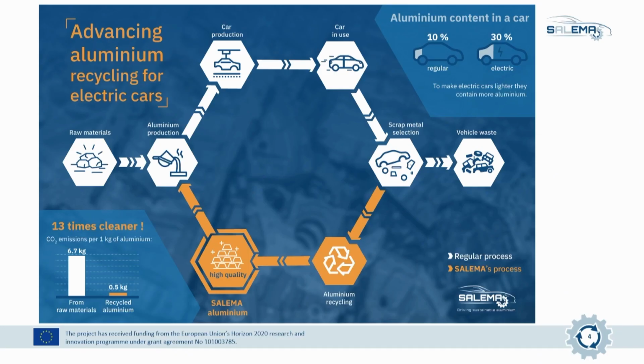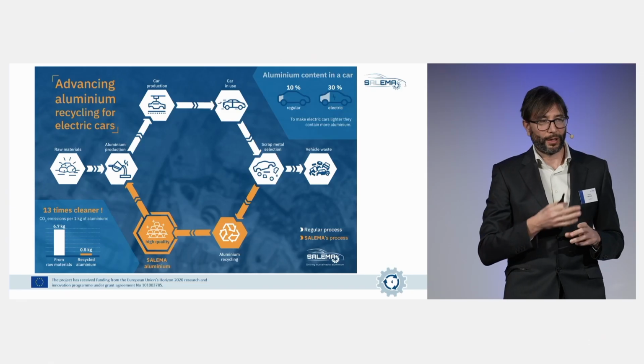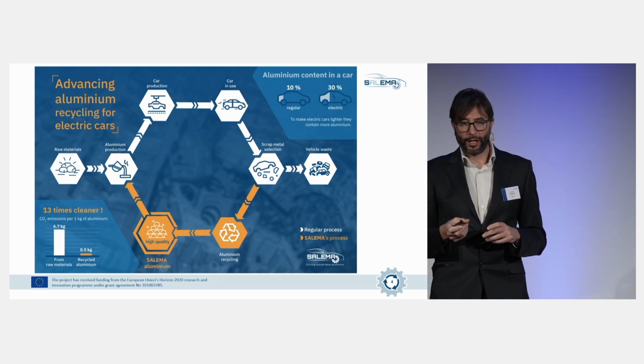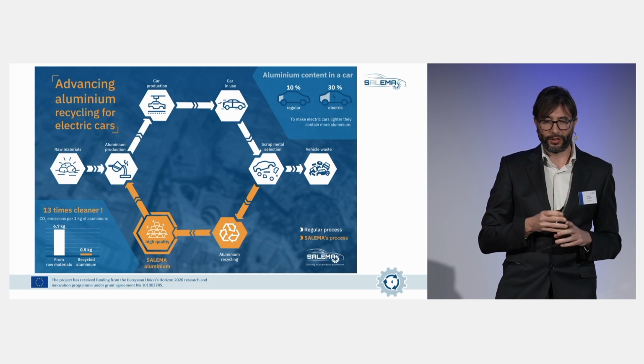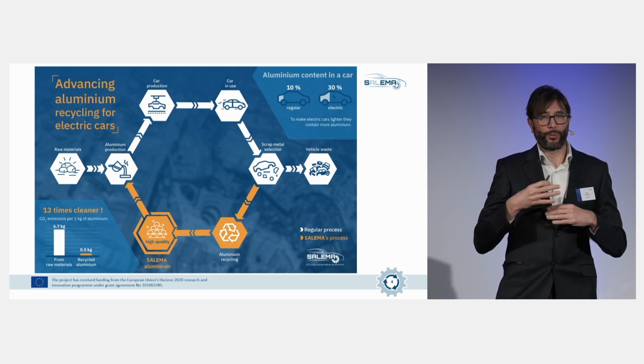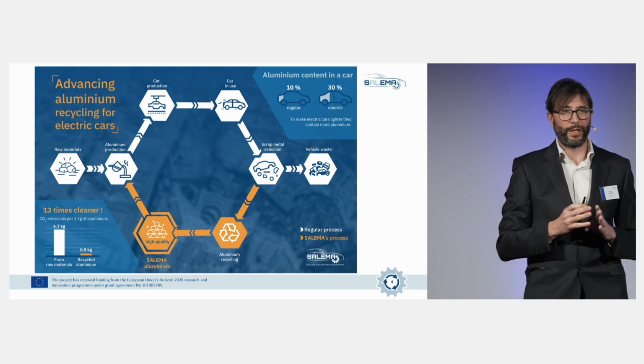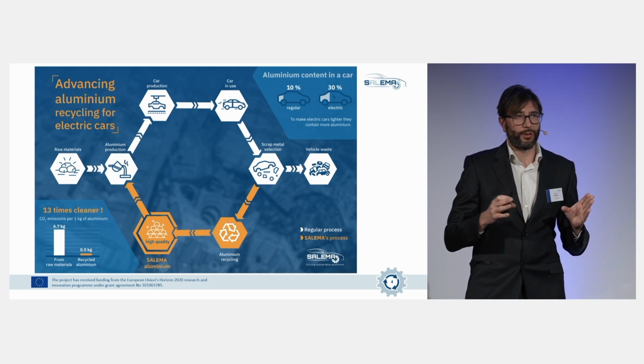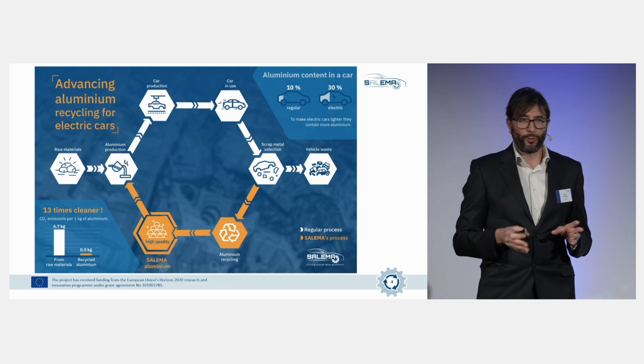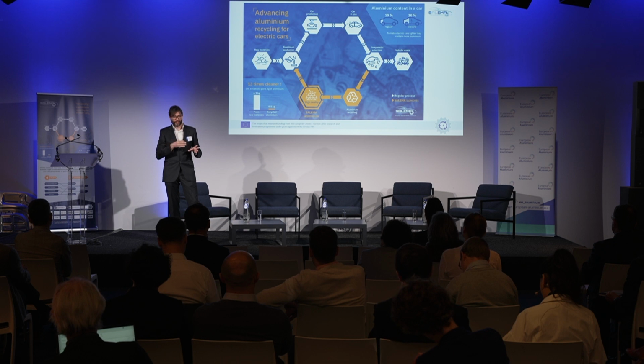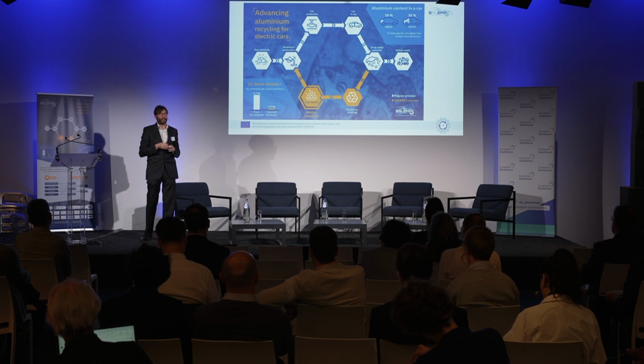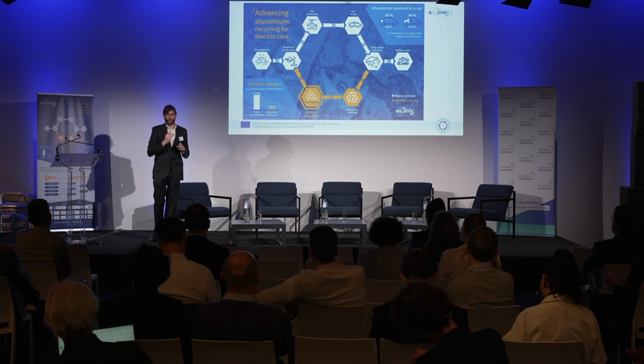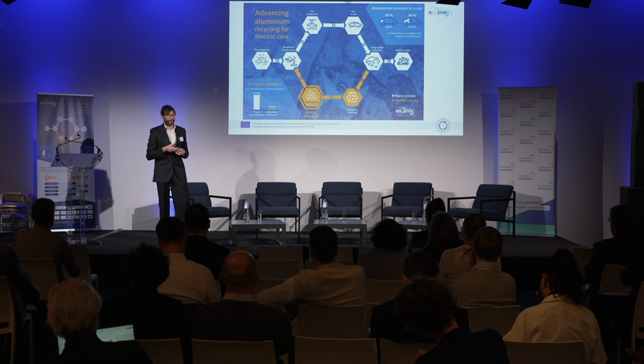Okay, so focusing on this second approach, what we have done is try to close the loop and to recirculate the end-of-life scrap to produce new high-performance aluminum alloys, new high-performance products. And for that, we have addressed two issues that we will discuss later. One is the sorting, so improving the quality of the scrap, to have better scrap with a narrow and homogeneous composition. And the second one has been to increase the impurity level present in alloys, to evaluate what is actually happening if we are increasing some impurities that are limiting the presence of scrap in the aluminum alloys.